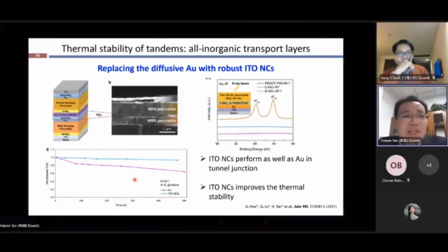But still, as we showed previously, we use 1 nanometer thick gold in the tunnel recombination junction. And we found that if we use the porous nickel oxide nanocrystal film as the hole transport layer for this bottom junction, the gold will diffuse through the nanoporous nickel oxide film and into the perovskite film. So this will be very bad for the device performance.